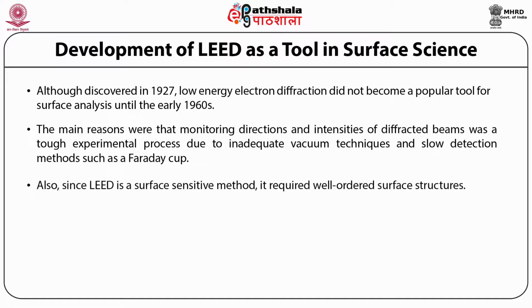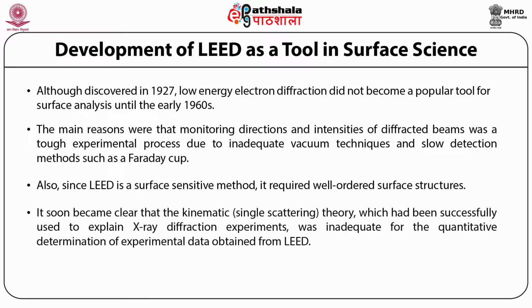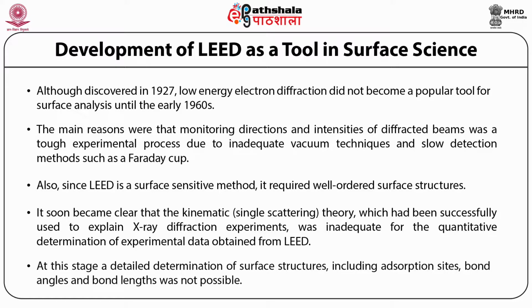Also, since LEED is a surface sensitive method, it required well-ordered surface structures. It soon became clear that the kinematic single scattering theory, which had been successfully used to explain X-ray diffraction experiments, was inadequate for the quantitative determination of experimental data obtained from LEED. At this stage, a detailed determination of surface structures including adsorption site, bond angle and bond length was not possible.